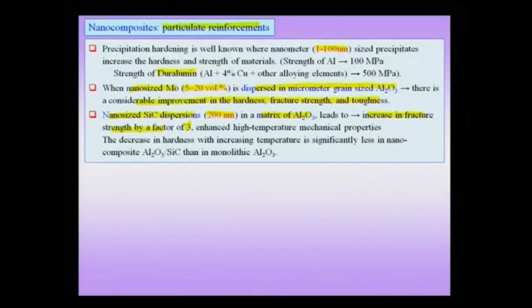So, by adding silicon carbide dispersions in the nanoscale, you can get an increase in fracture strength of about a factor of 3, which is a pretty good increase. The high temperature mechanical properties are also pretty good, and you know, typically these ceramics do find applications at high temperature, and this would be a good thing to add, actually, silicon carbide.